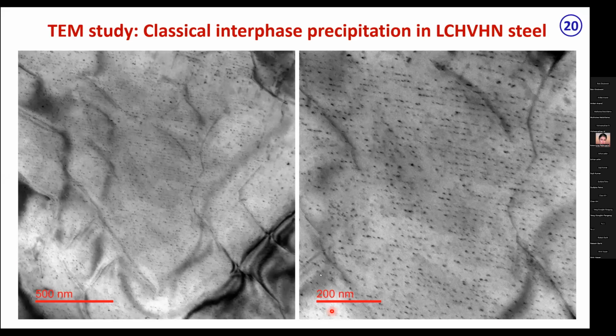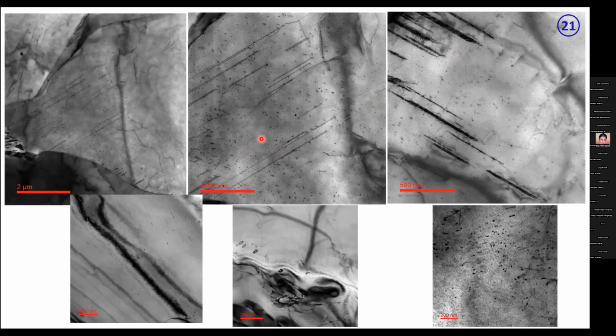Overall, these are the findings, and we have characterized the precipitates, and this process is going on. Nice interphase precipitation. These are some of the images. You can see in this low carbon, high vanadium, high nitrogen steel, these are there. Nice interphase precipitation of vanadium carbonitride, as we expect in this kind of steel during transformation. Sometimes we have found some elongated features also. We are studying whether these are fibrous carbides or something else, but these are quite interesting to look into.